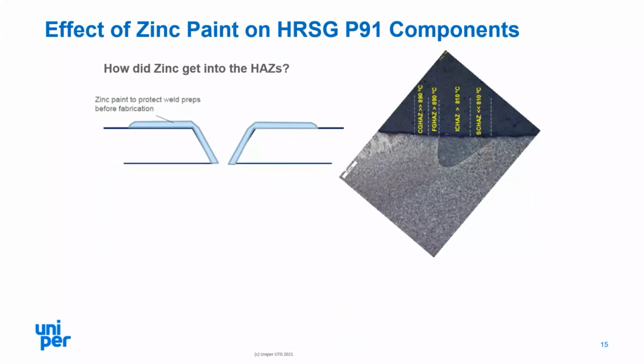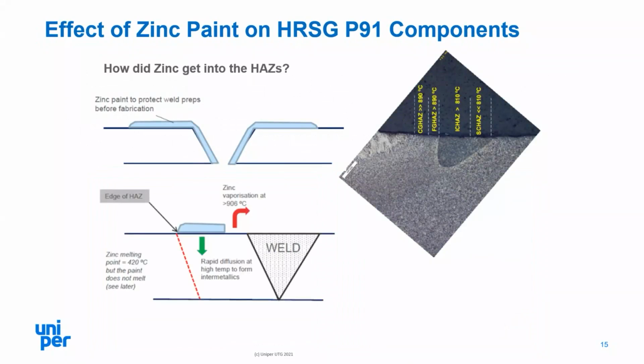In seeking to explain how the zinc got into the heat affected zones, what was apparent was that the weld preparations had been painted with zinc prior to fabrication to offer some level of corrosion protection. When welding was achieved, the material immediately adjacent to the weld itself, local to the fusion boundary, saw the zinc vaporizing off at temperatures above 900 degrees centigrade. However, within the intercritical heat affected zone, the zinc would have been molten and rapidly diffused into the material adjacent to it.